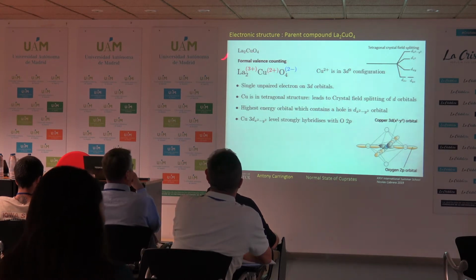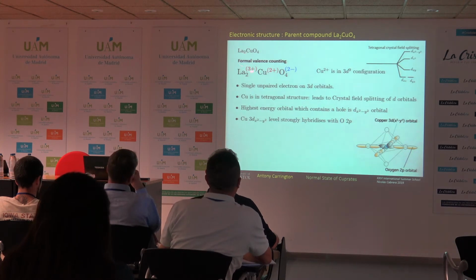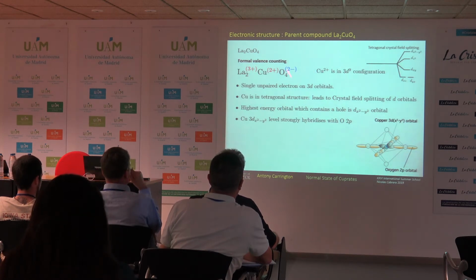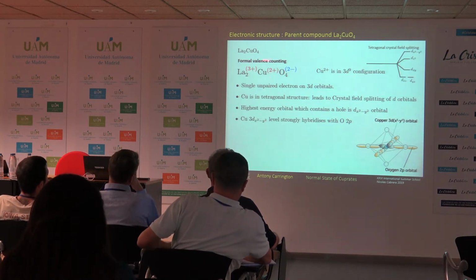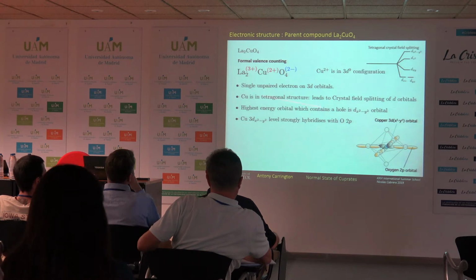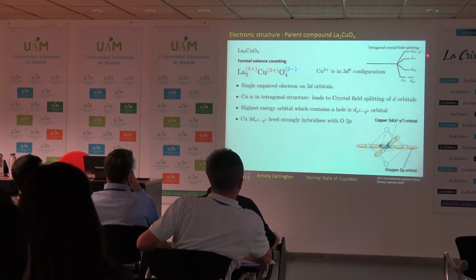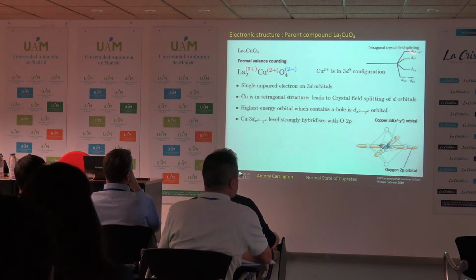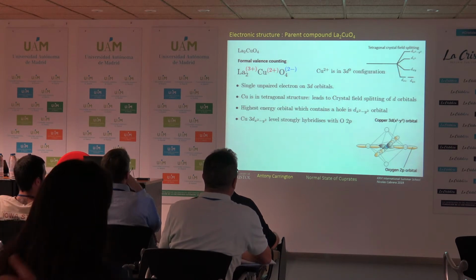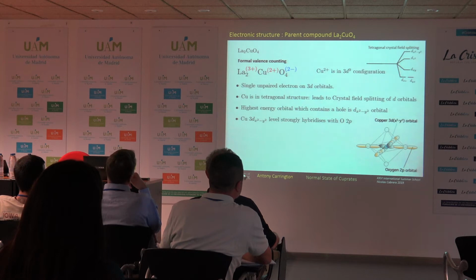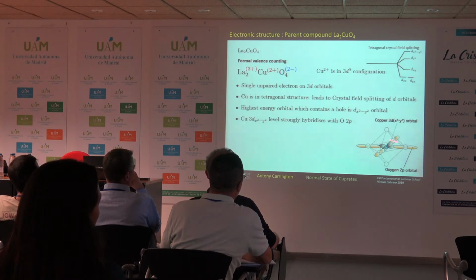Okay, so a very basic electronic structure. If you take the parent compound, lanthanum 2 copper oxygen 4, and assign some formal valencies, lanthanum is 3 plus, oxygen is 2 minus, and if you add up all of the charges, you work out that copper must be in a 2 plus state. It's in a tetragonal crystal field, and so the d levels split like this, and you end up with a single unpaired electron in the copper d x squared minus y squared level. That electron in the copper 3d level then hybridizes with an electron in the oxygen 2p level and forms a coherent state, forms a bond like that.